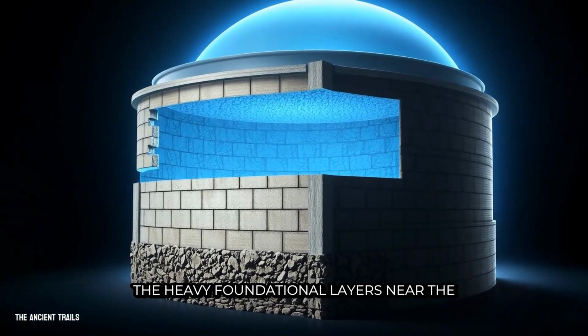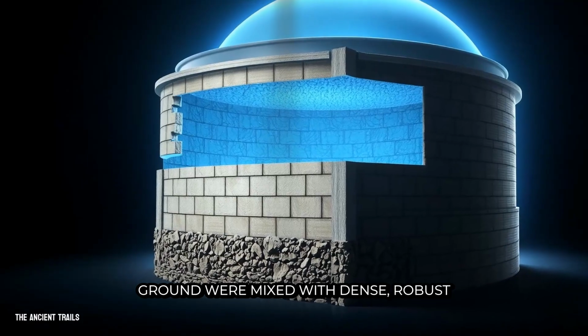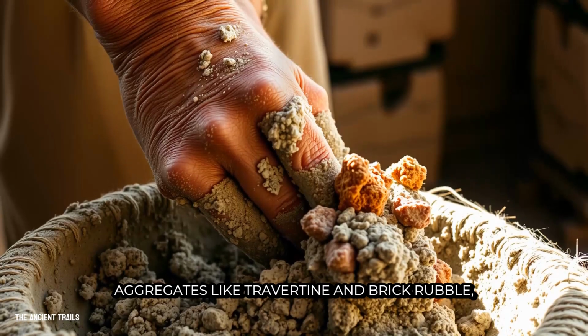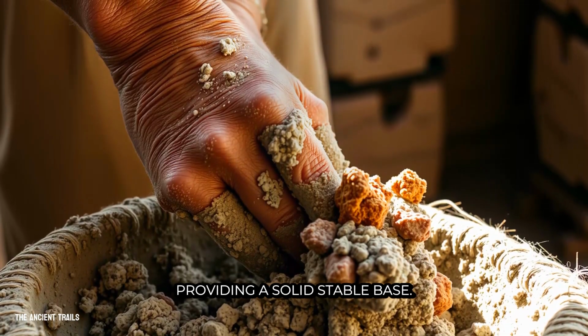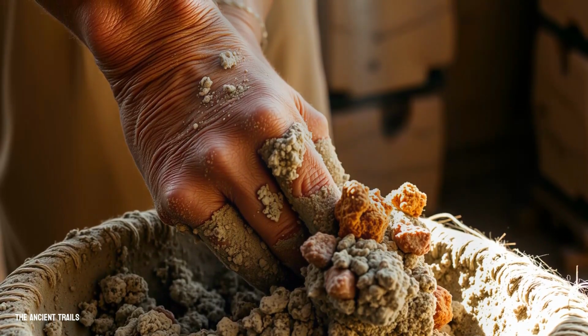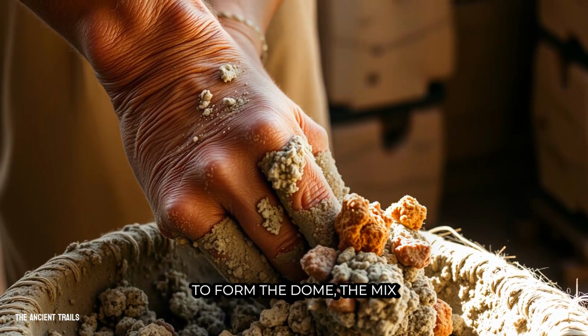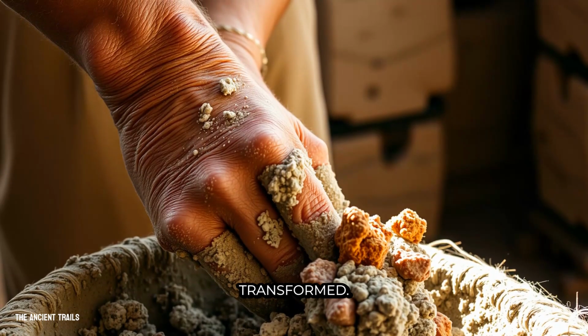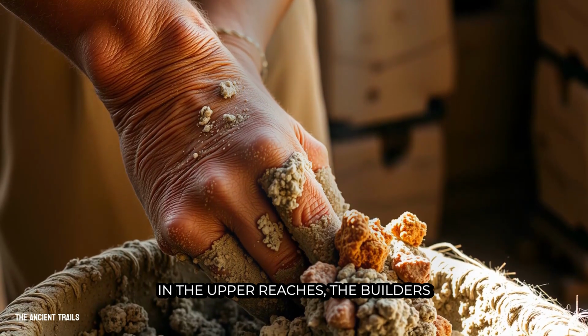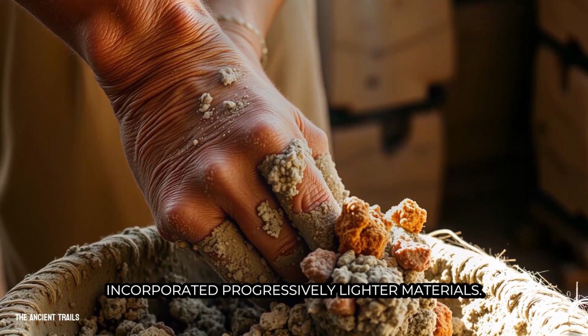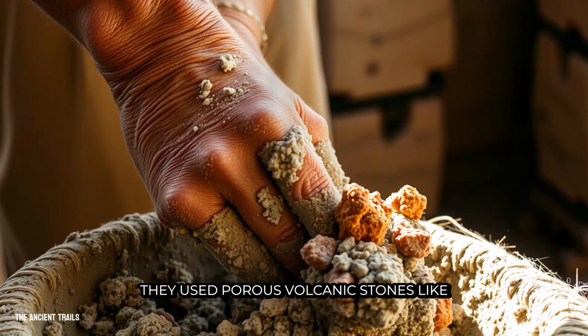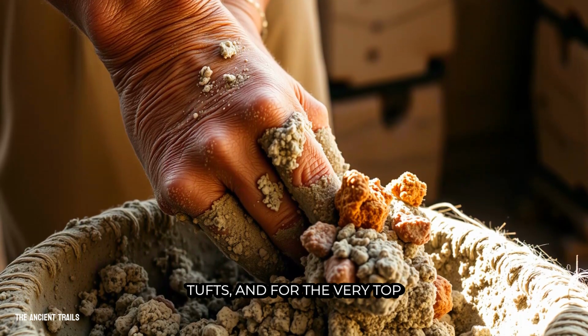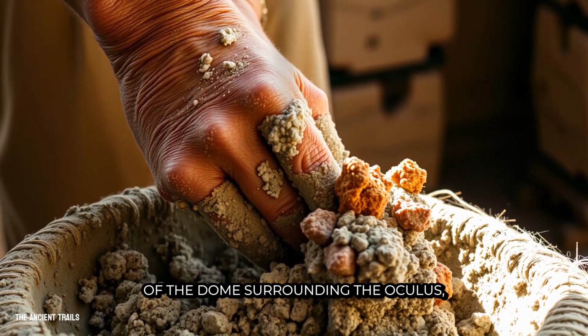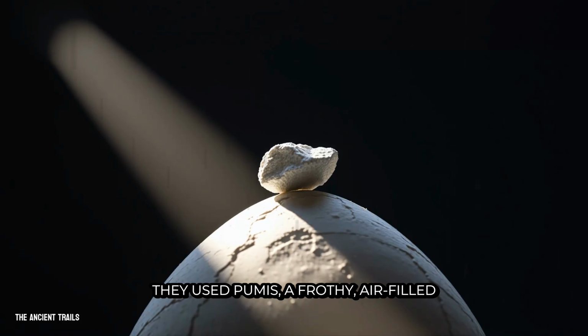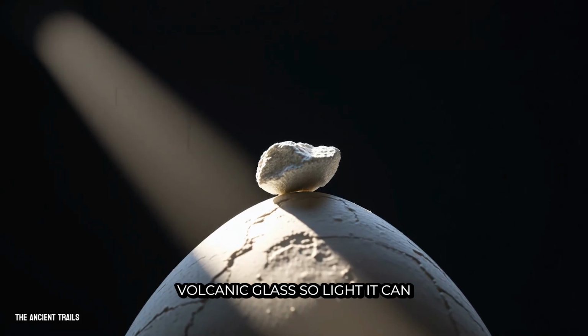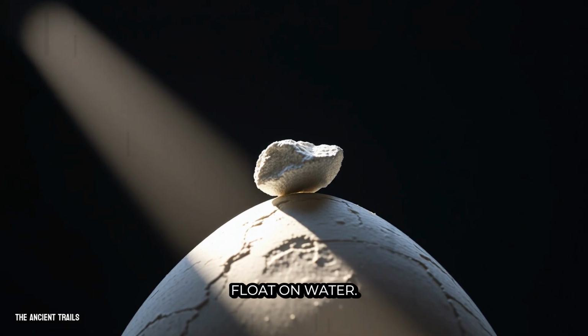The heavy, foundational layers near the ground were mixed with dense, robust aggregates like travertine and brick rubble, providing a solid, stable base. But as the walls curved inward to form the dome, the mix transformed. In the upper reaches, the builders incorporated progressively lighter materials. They used porous volcanic stones like tuff, and for the very top of the dome surrounding the oculus, they used pumice, a frothy, air-filled volcanic glass so light it can float on water.